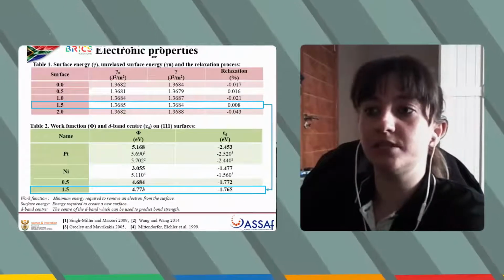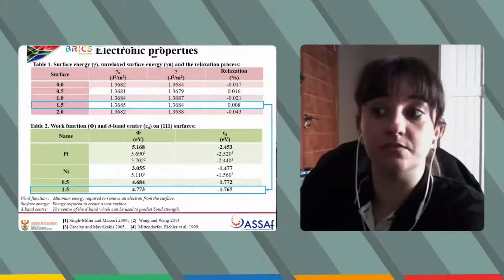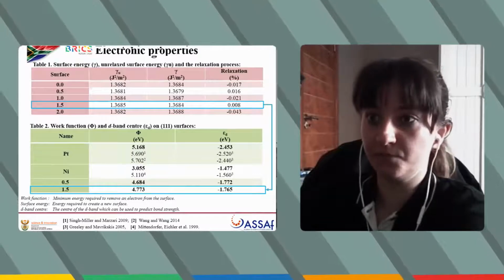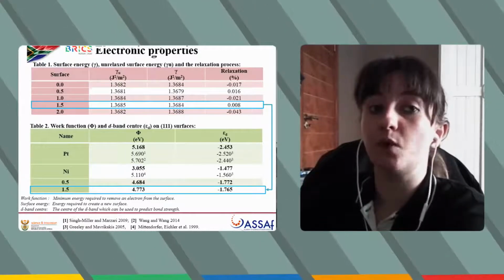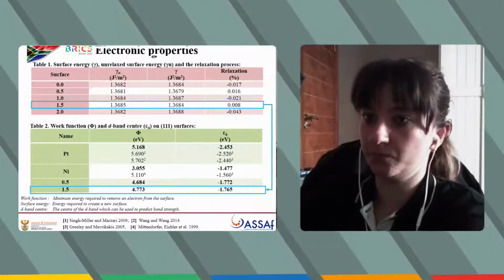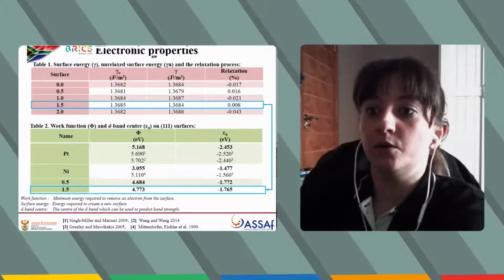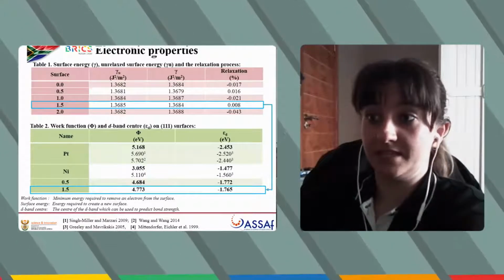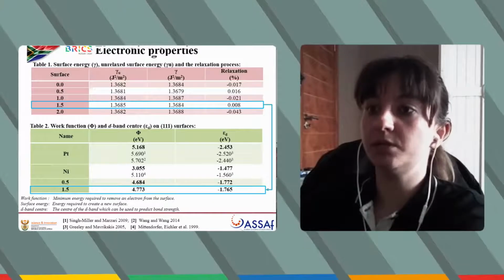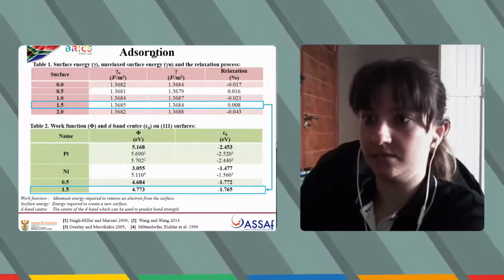The relaxation percentage shows the stability of a surface before and after optimization. From the table, you can see that it's the 1.5 surface termination. The work function and the D-band center were investigated to predict the adsorption ability of the bimetallic surfaces.